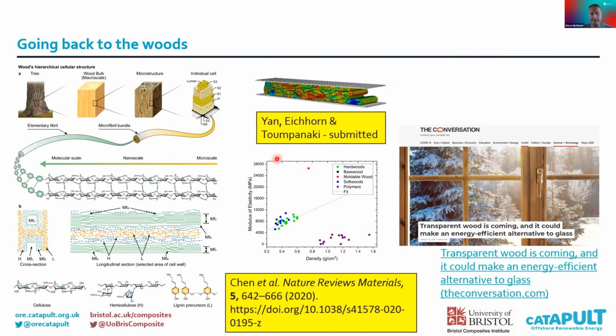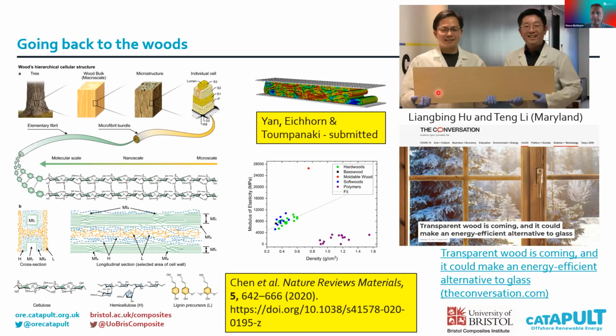We've been compressing it in simulation here, but working with a group in Maryland, they've been able to make large pieces of wood that have really high mechanical properties. So here's an Ashby diagram. These are some typical woods here. So we can get a very, very high modulus of elasticity. It's a higher density than these bits of wood here, but certainly exceeding anything that's been seen in nature so far. And they're also able to make it transparent.